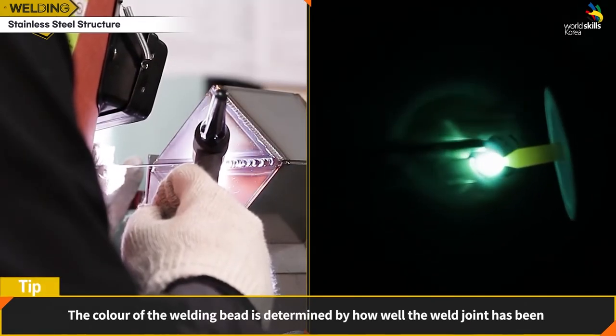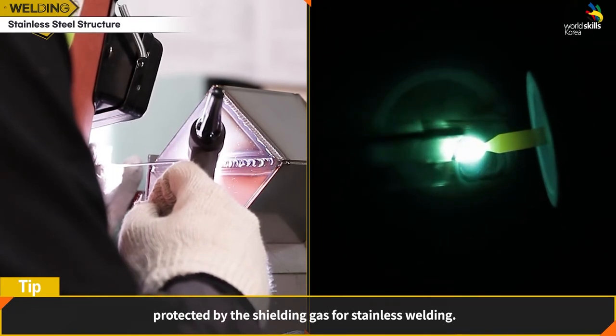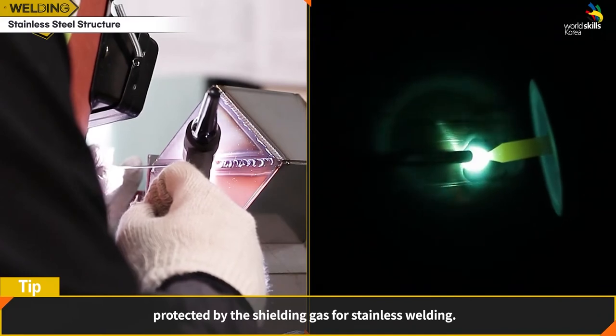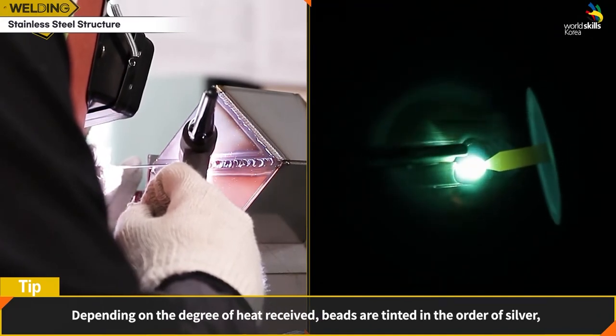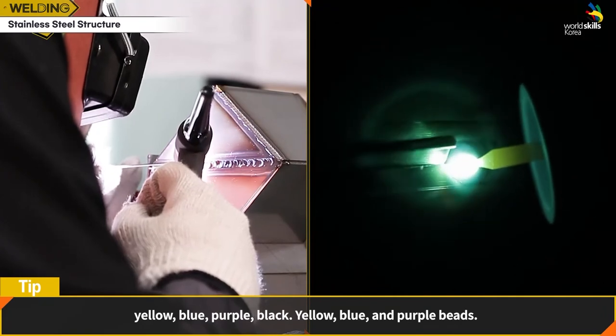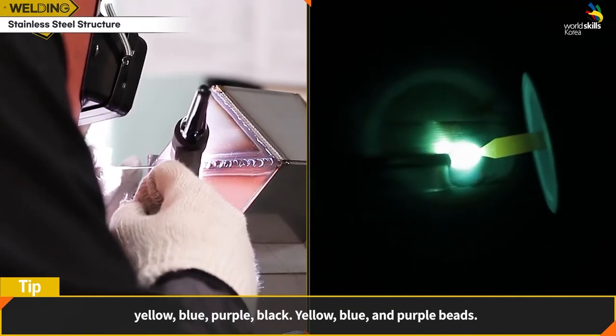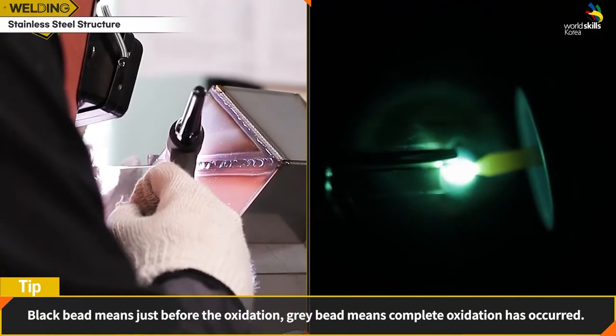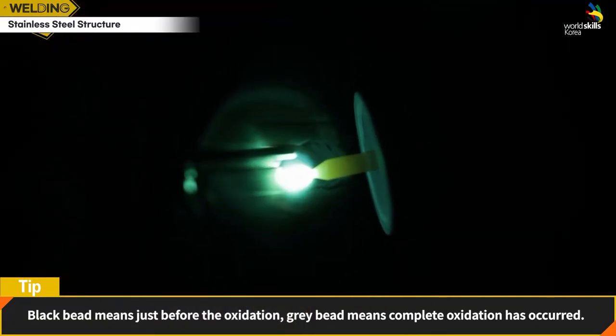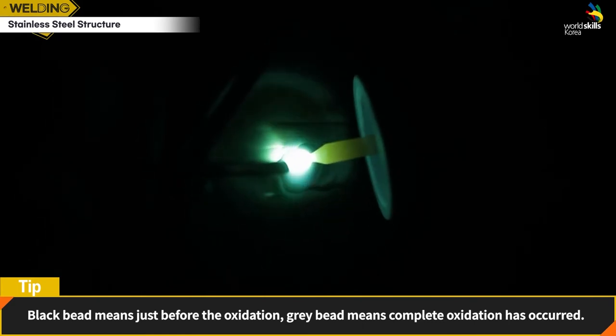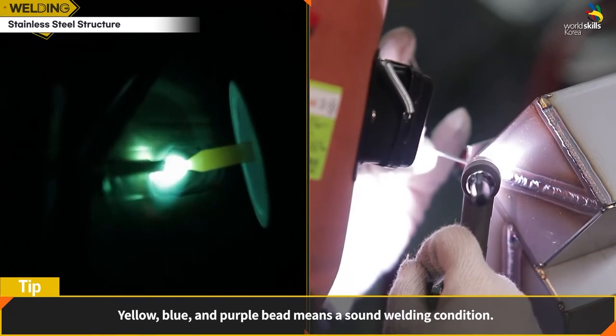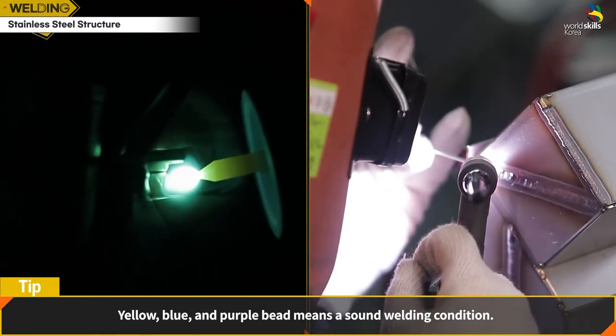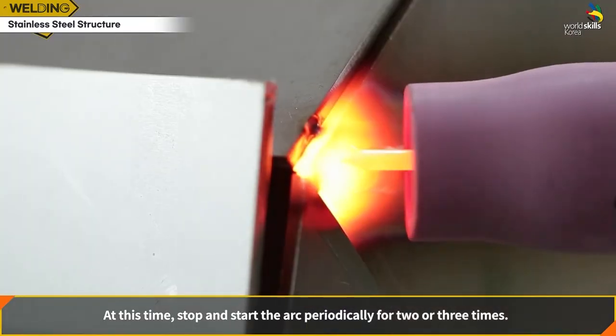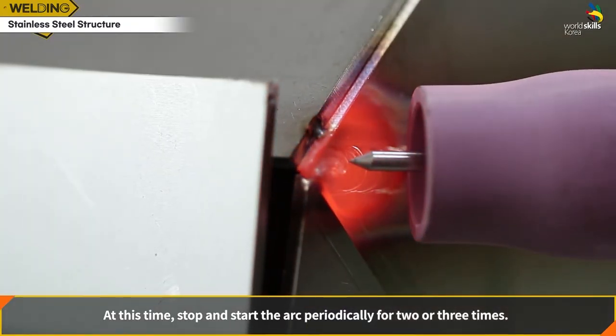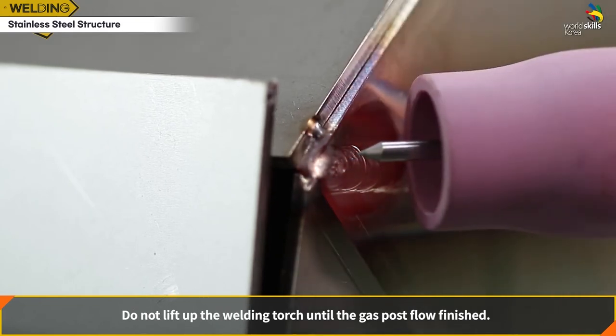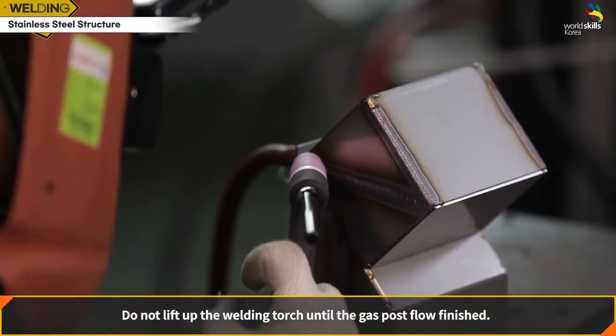For stainless welding, the color of the welding bead is determined by how well the weld joint has been protected by the shielding gas. Depending on the degree of heat received, beads are tinted in the order of silver, yellow, blue, purple, black. Black bead means just before oxidation. Gray bead means complete oxidation has occurred. Yellow, blue, and purple beads mean a sound welding condition. At this time, stop and start the arc periodically 2 or 3 times. Do not lift up the welding torch until the gas post flow has finished.